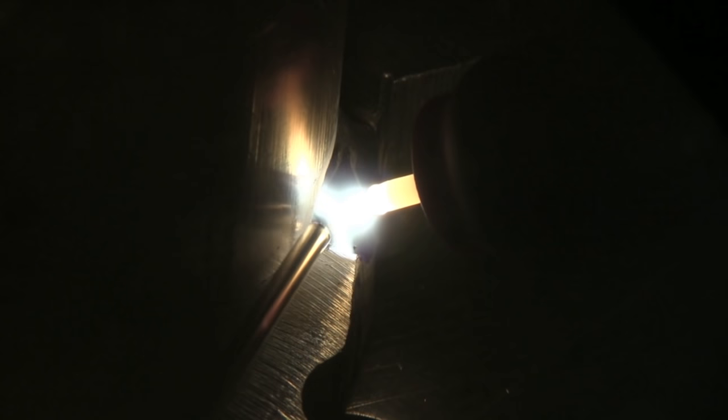Again I'm 77 Hertz, I really kind of need a lot of heat on this half-inch thick metal and the low Hertz like that, slightly higher than a transformer machine but just I kind of like it, I really couldn't really explain why other than with that helium mix it puddles immediately. I don't have to wait around to get a puddle started and it worked out pretty well.